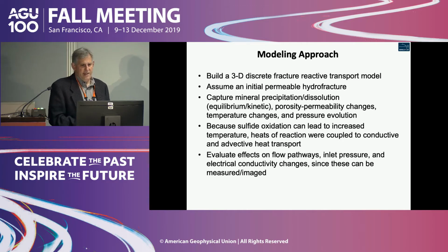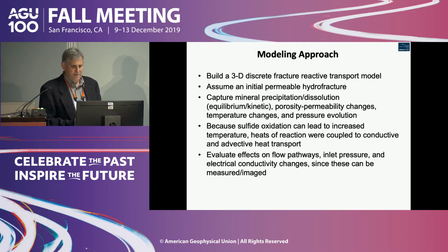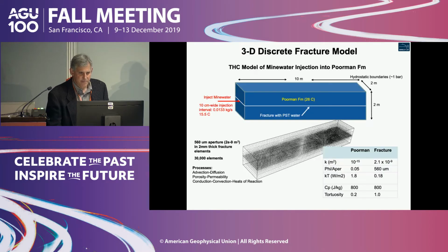And we also looked at flow pathways, we looked at the inlet pressure changes, and we also looked at electrical conductivity changes of the fluid. I'd thought about that for a long time, and then Pat said, oh, they have some great data, here are some papers, and we put it in the code, and it's actually pretty useful for mapping out compositional changes.